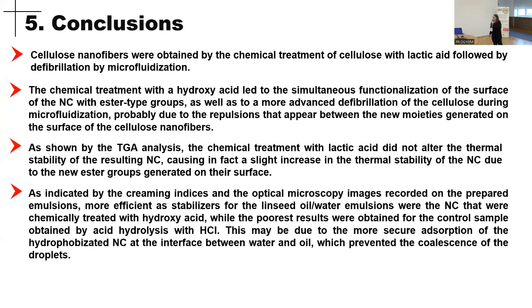As shown by the thermogravimetric analysis, the modification with lactic acid led in fact to an increase in the thermostability of nanocellulose, and we also have seen that the cellulose that was chemically modified with lactic acid acted as a great stabilizer for Pickering emulsions, while the control sample obtained with hydrochloric acid, which is a strong acid, did not perform as well in this aspect.